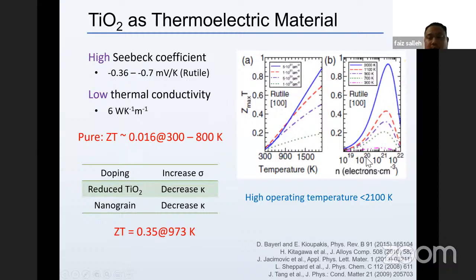In general in thermoelectric material, as I mentioned, it strongly depends on the material properties: the Seebeck coefficient, electrical conductivity, thermal conductivity, and also the carrier concentration. So if you see here, theoretically it can have the optimum value of the dimensionless figure of merit at a higher concentration of carriers, and it can achieve almost one. It has a high Seebeck coefficient already reported. Rutile is around 0.36 to 0.7 millivolt per Kelvin, and it has quite low thermal conductivity, around 6. And if we look at pure TiO2, the ZT is around 0.016 at this kind of temperature. So it's still low if we compare with other conventional material.